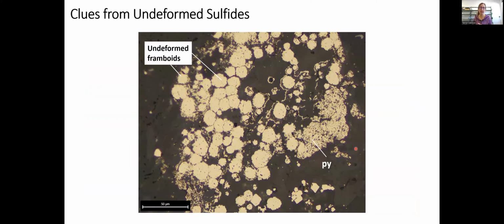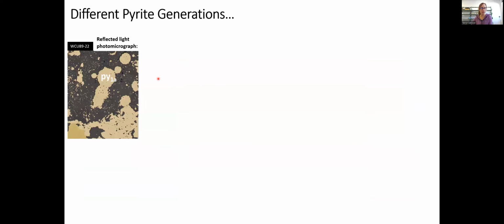Now, we're going to see what we can learn from some of the undeformed sulfides. So here we have a little pyrite framboid. These are little round shapes, and they are typical of pyrite that forms at fairly low temperatures, maybe during diagenesis, maybe low temperature hydrothermal activity, and often with a lot of bacterial or microbial activity. So this is probably some of our really early pyrite, and we'll call it pyrite 1A.